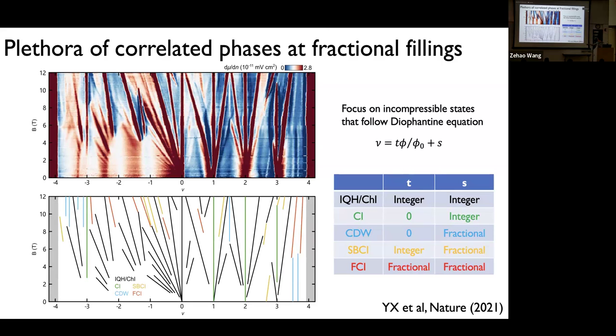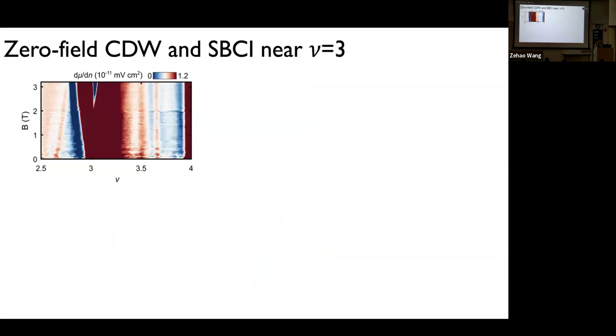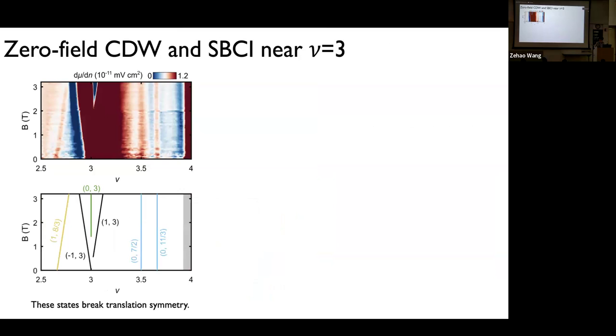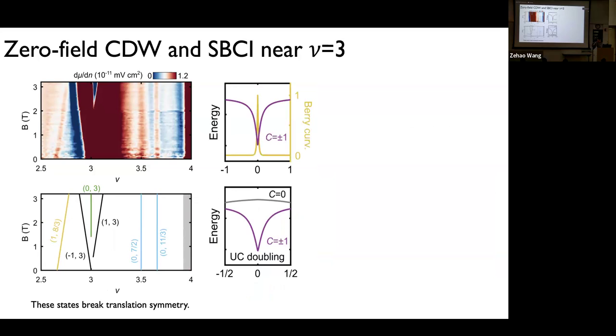To do that, I'll first focus on carrier density between 3 and 4, because that's a place where we understand the system better, because the system can be well approximated by just one single Chern band. So this is the low field portion, zero magnetic field, and we see a number of states that have fractional intercept. However, they either have no slope or they have integer slope, and that's not what we want.